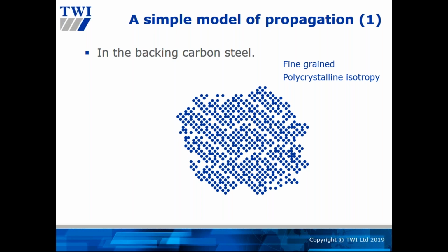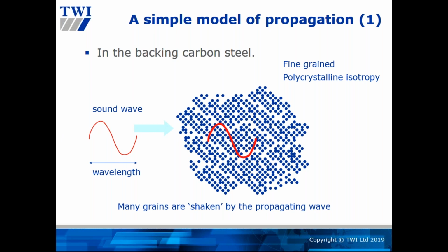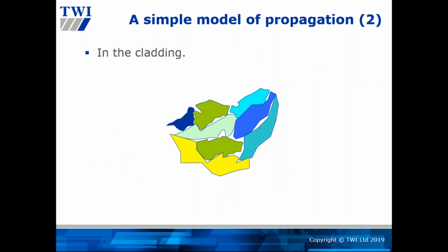So carbon steel is described here as a fine-grained polycrystalline isotropic material with fairly small refined grains. And when a sound wave, which I'm representing by what looks like a wave, travels through it, what it essentially does is it picks up a lot of those grains and shakes them, and in that way it propagates through the material. But when you are looking at the cladding, so when that sound moves into the cladding, you have a slightly different material through which it has to